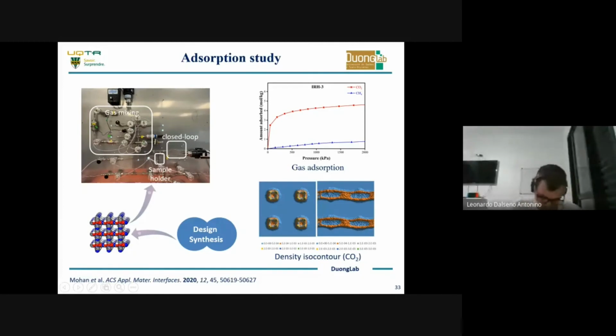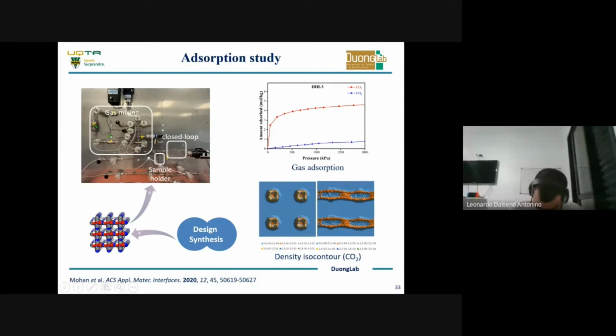We collaborated with another team to do some simulations, because we were interested in understanding why our materials are so selective. They used Grand Canonical Monte Carlo to compute this density isocontour, and we found that the CO2 mainly sticks on the wall, while methane, for example, doesn't have any specific positions. Also, where you have water, you don't have methane, because methane is hydrophobic. So the coordinated water that I was talking about here is interesting for gas separations and gives us good selectivity.